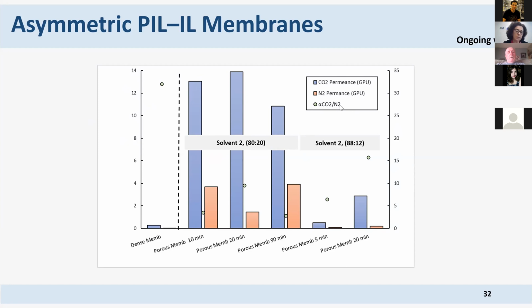So you can see that by playing around with asymmetric membranes, this is more than asymmetric membranes, it's already porous membranes, we greatly increase the flux for both gases, and we also compromised a lot the selectivity, okay? Then we tried to adjust this solvent a little bit more by playing with the quantities of the two components of the solvent. And here we can see that we don't know yet if we have a porous membrane, because we did not take it to the SEM, or if we have an asymmetric membrane. We greatly decrease the flux, and the selectivity is again coming up.